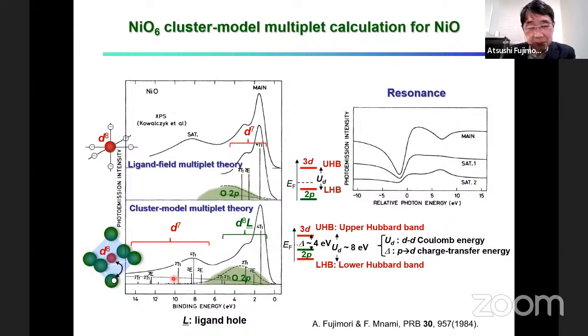In order to reproduce the data, the D7 multiplet is actually deep, several electron volts below the chemical potential. So this is enhanced. The main band is suppressed. This kind of electronic structure turns out to be the real, true electronic structure.